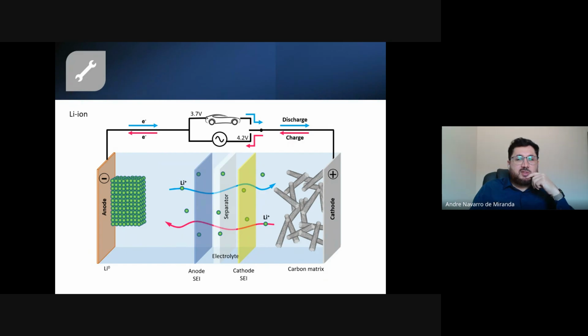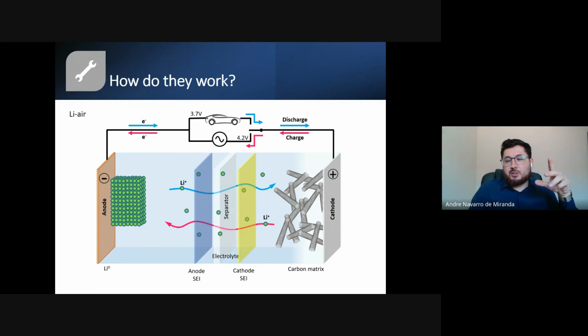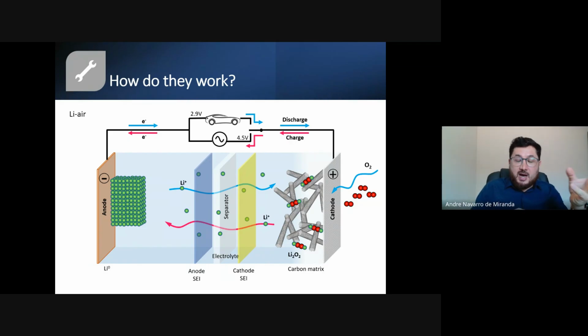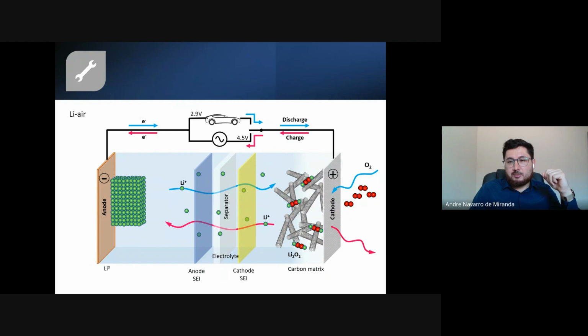And you have another possibility. Someone thought, well, let's change this cathode. Let's not use a transition metal oxide. Let's use a carbon matrix. Then we open this battery to the air, to the atmosphere, and we capture oxygen. In this process, we can form lithium peroxide. So this is not an intercalation process, which is what happens in lithium-ion batteries. This is a formation of a new product. And in this process, you have a lot of energy stored in the battery. In the discharge process, we have formation of lithium peroxide. And then in the charge process, when we connect the energy, we have the decomposition of the lithium peroxide. So this is how lithium-oxygen batteries work.